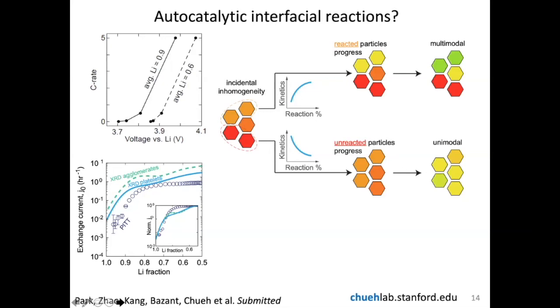So in both situations, you start with the same level of inhomogeneity, but in the case of kinetics getting faster and faster on charging, the heterogeneity is amplified. And on discharging, the same heterogeneity is diminished because the kinetics is getting slower and slower. So this is the effect of autocatalysis imparted by how the exchange current density depends on the extent of delithiation.